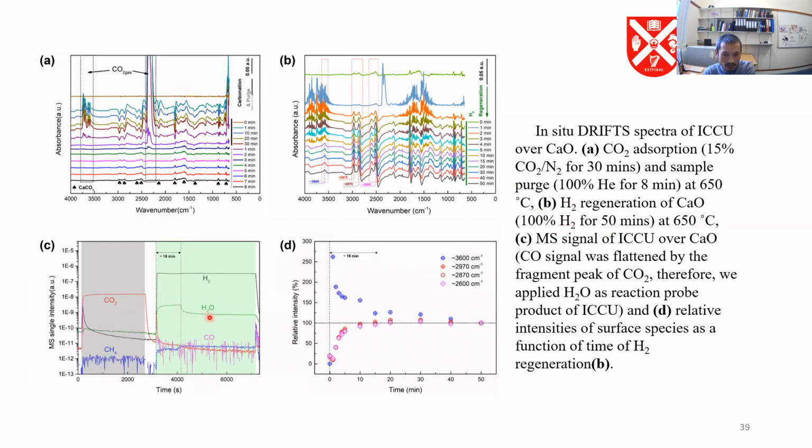You can see here from the gas analysis, the first 60 minutes have a lot of water produced, and that is related here. And then we have the hydroxy groups, mainly from water, and they can also react with calcium oxide. That is what we are trying to explore the reason behind, but it's still not quite clear at the moment. But anyway, I think the hydroxy group and the formation of water play a key role in this process.